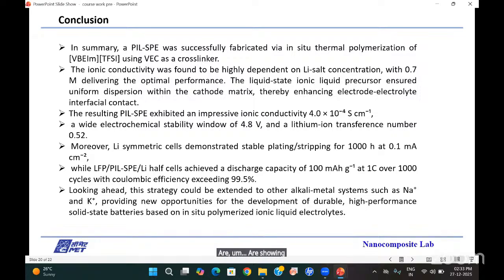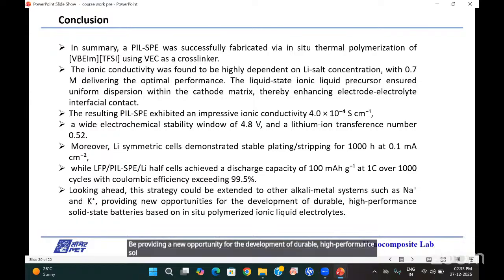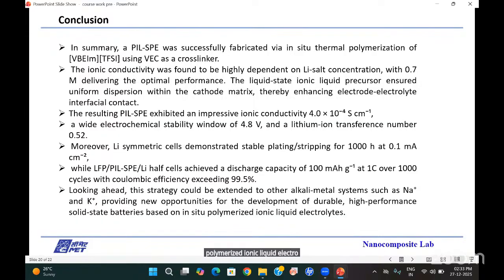showing at 1C for 1000 cycles a discharge capacity of 100 milliampere hour per gram, and an extended Coulombic efficiency up to 99.5%. Looking ahead, this strategy could be extended to other alkali metals, that is sodium and potassium, which can provide a new opportunity for the development of durable, high performance solid state batteries based on in situ polymerized ionic liquid electrolytes.